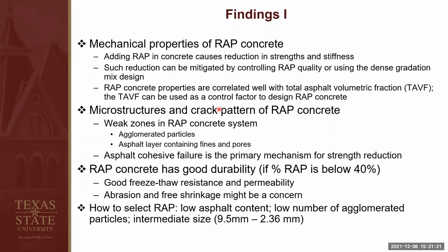stiffness. Based on our microstructure analysis and crack pattern study, we found the agglomerated wrap particles are the weak zones in the wrap concrete system, and the asphalt area is also a very weak point in the wrap concrete. And we concluded that asphalt cohesive failing is a primary mechanism for the strength reduction. We also did a durability test to evaluate the wrap concrete with up to 40% coarse wrap replacement. And we found our wrap concrete had a very good freeze-thaw resistance, and the permeability of the wrap concrete is also satisfactory. However, the abrasion resistance and the free shrinkage might be a concern.